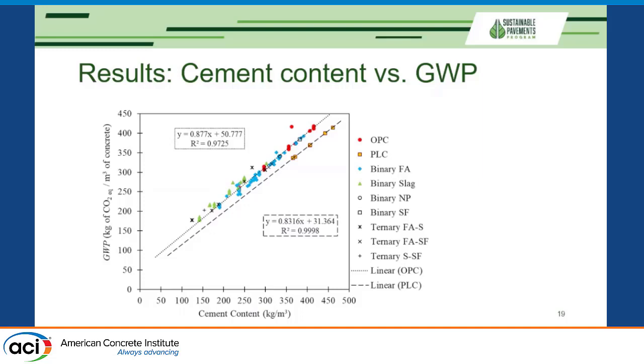We have shown you similar trends, and you can see these mixes with ordinary Portland cement, high cement contents, highest global warming potential, these little red dots. Portland limestone cement, that's a new thing we have included here, and you can see the line for Portland limestone cement also has a strong linear correlation, but everything, GWP, is lower. It's proportionally lower to that of mixes with type 1 or type 1/2 cement.